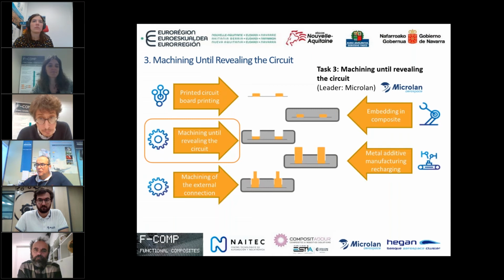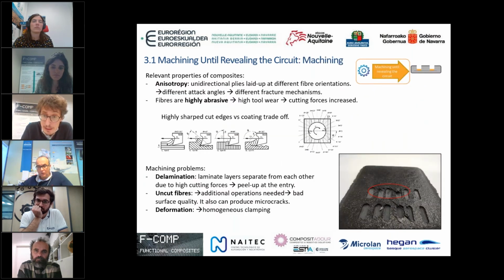For task number 3, that is the revealing of the circuits, the leader was MICROLAN Aerospace. Here, as per the use of composites, there are 2 main issues. One is the anisotropy, that makes the fracture mechanism of the part when doing the machining different depending on how the tool goes against the fiber. So that generates different angles, so we have different breaking mechanisms. Another point is that the fibers themselves are very abrasive, so the tool wear is very high.